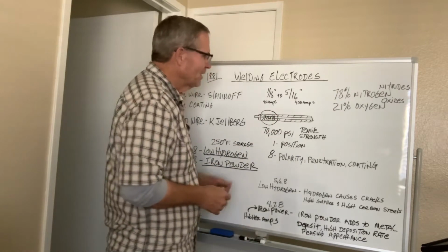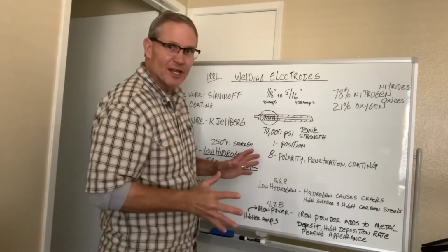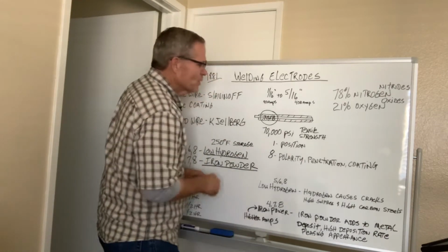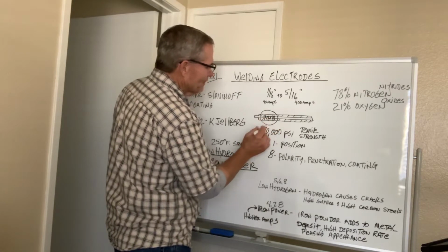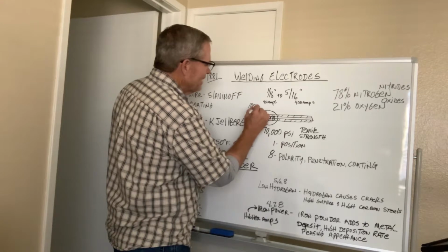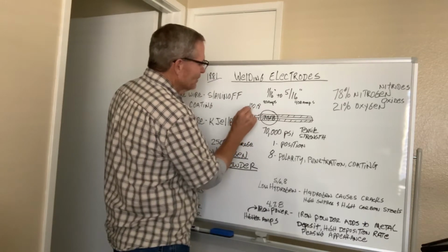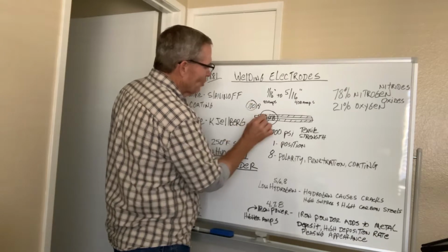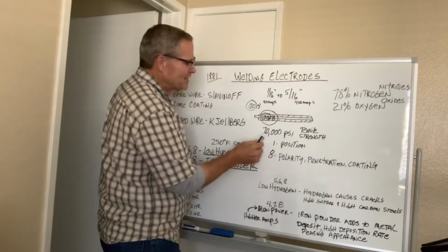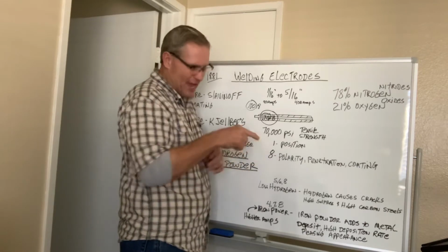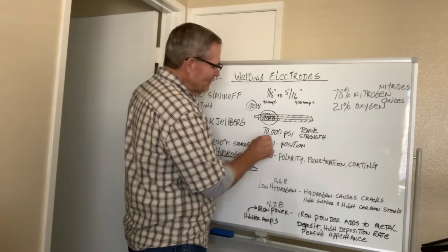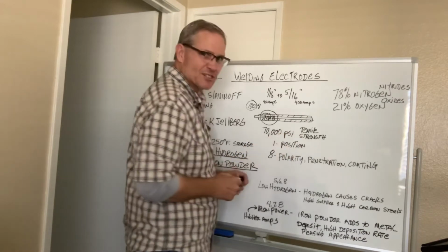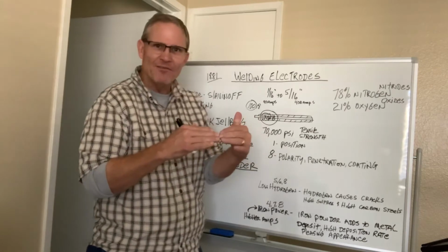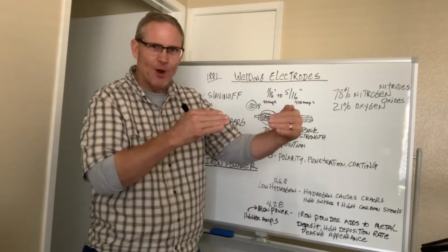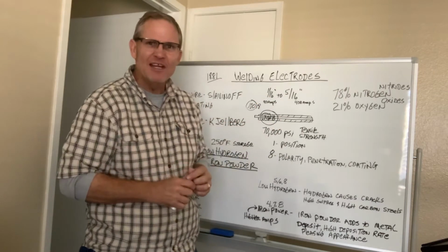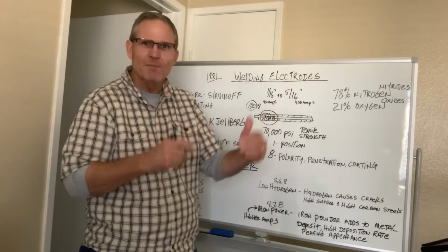And I wanted to take just a moment and talk to you about the numbers, the markings on the electrode itself. The way we do this is we always leave the last two numbers. So even if this was a 7018 electrode, we would leave the last two numbers, but you key in on the numbers that are left, or in this case, it's a 70. And what they're guaranteeing is that your completed weld, after you've welded, you're guaranteed to have 70,000 pounds per square inch of tensile strength. And what that means is that as you have a finished weld and you try to pull that piece apart from what you just joined, it would take 70,000 pounds per square inch to actually pull it apart.